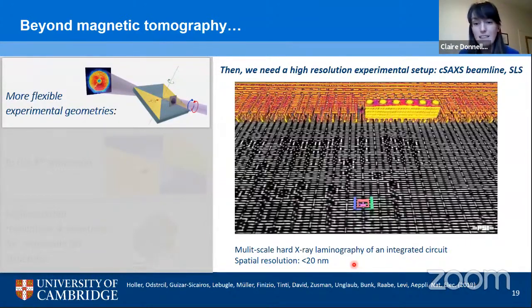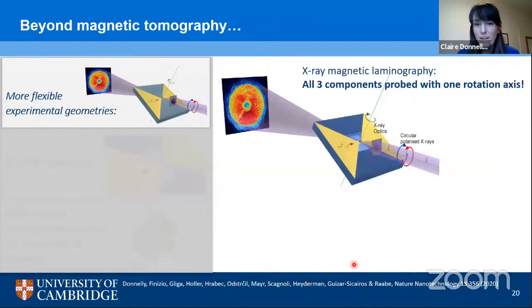demonstration of magnetic laminography. So one last point about this technique before we get into the results, and that is that it actually has another advantage in that with one single rotation axis, we're able to probe all three components of the magnetization. Now, what this means is that our measurement actually becomes so much simpler. We can measure all of the information that we need with a single rotation axis, and therefore don't need to be changing different sample setups and everything halfway through the measurement. So now onto our demonstration.